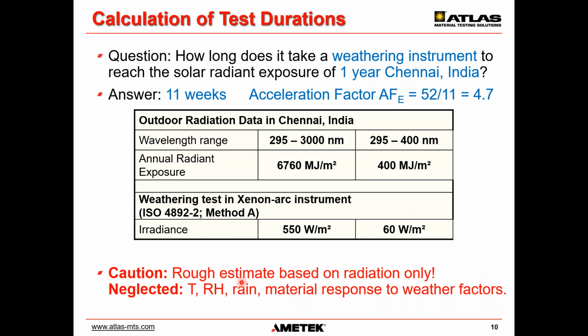So now let's go back to the red disclaimer that I had put down here. This is only a rough estimate based on radiation only. What we neglect is temperature, relative humidity, rain, and all secondary weather factors as well. And the most important neglected property here is the material response to the weather factors. So we are calculating acceleration factors only based on weather data. Acceleration factors should always be determined, not calculated, by looking at the material response, right? So it is very important to know what we just did. It's a very rough estimate that I calculated here in this short calculation.